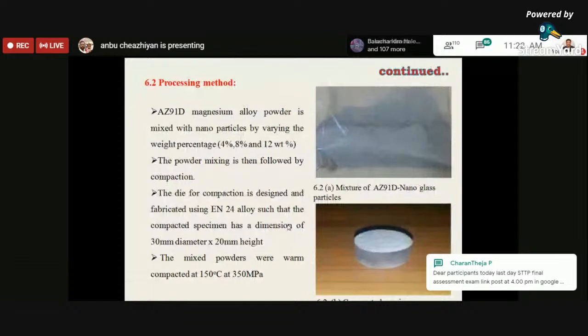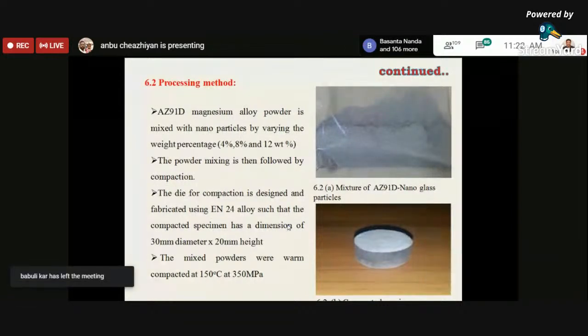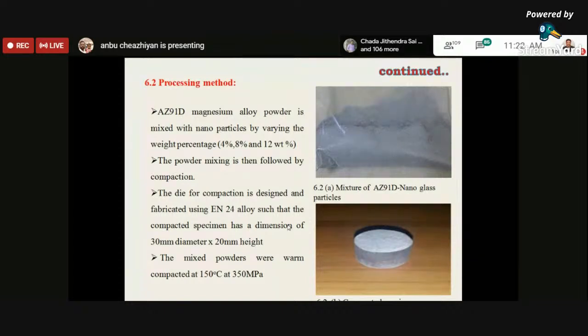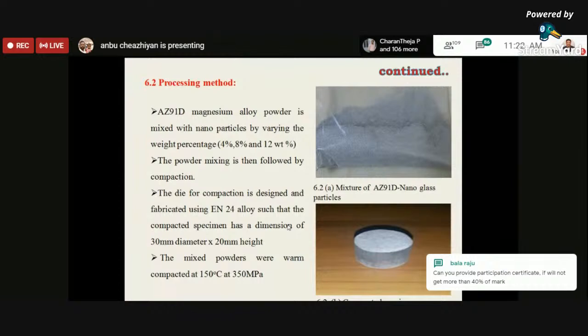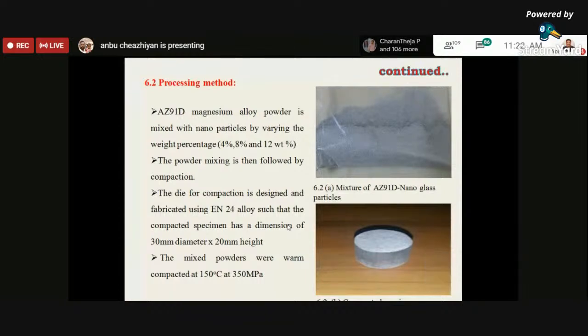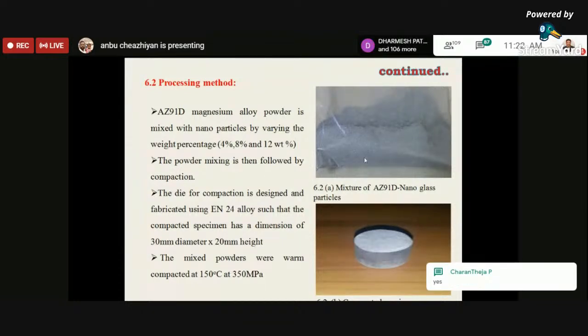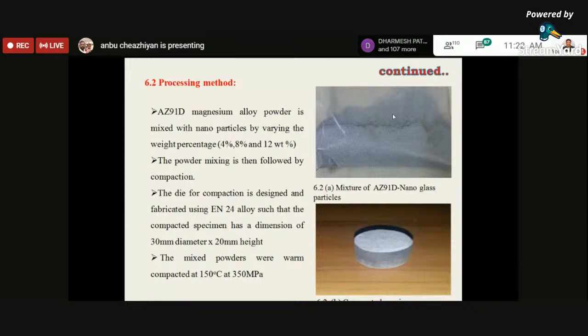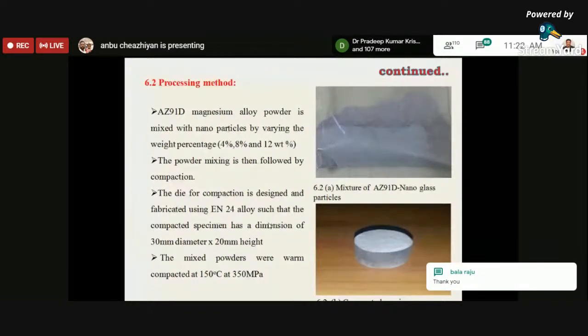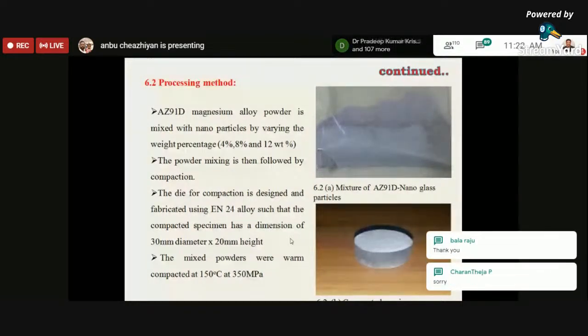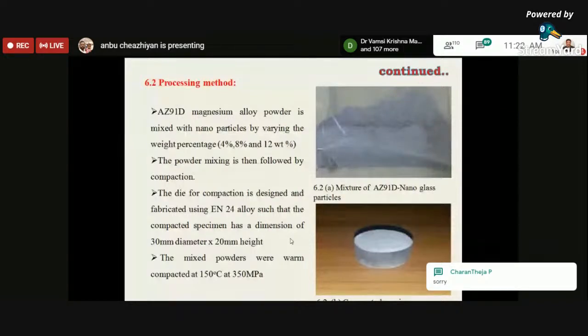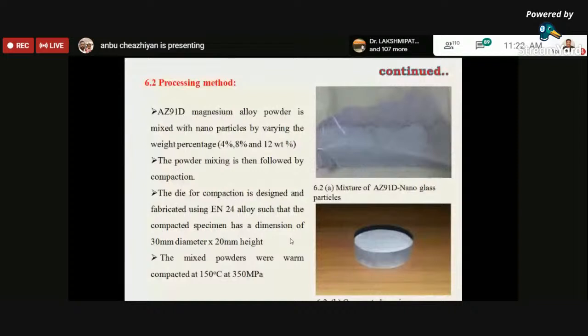Here we have blended the reinforcement particles with magnesium alloy powders by varying the weight percentage. Since it is a borosilicate glass, the wettability will be very poor, so we need uniform distribution throughout the matrix. For this powder matrix, we need to do it beforehand. So we took a bowl, and using a fan-like stirrer, we placed the reinforcement and matrix and stirred well, and from this we obtained the composite powder. We used EN24 as a die with dimensions of 30 mm diameter and 20 mm. After that, green compaction, and then sintering at temperature.